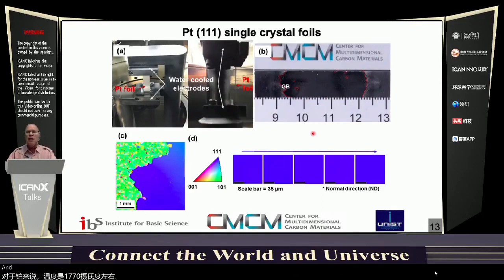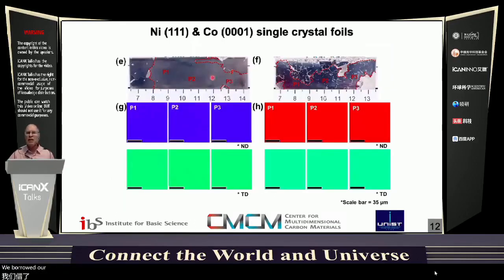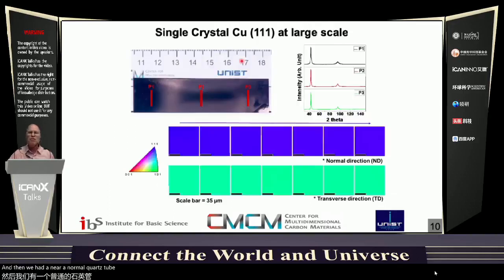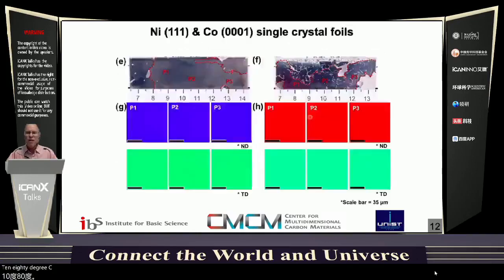And now we have an oven that we can hang platinum foils in, but as I mentioned, at that time we didn't. We borrowed our colleague's oven that was a large ceramic oven and worked near 1,400 degrees for nickel and cobalt. And then we had a normal quartz tube oven for the copper to heat it to about 1080 degrees C.